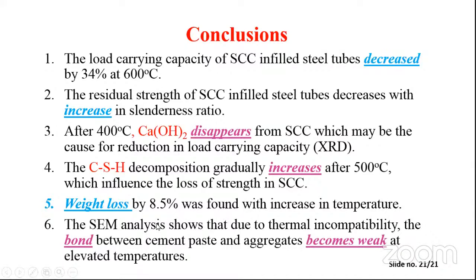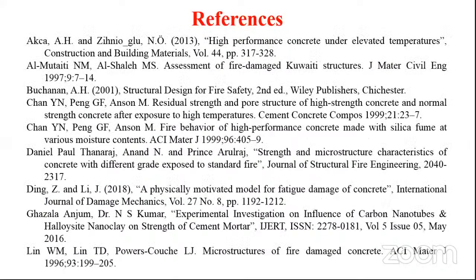By the SEM analysis, due to thermal incompatibility, the fine aggregate and coarse aggregate increase in volume. Because of that, the bond between the cement paste and aggregates becomes weak. That is also one reason why strength is lost in SCC under steel tube. So these are some conclusions drawn. These are some references. Thank you for watching.